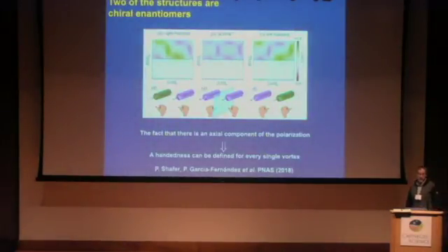And we can define a hand for all of them. So to do this, just take your right hand and then curl the fingers in the direction of the arrows. And then if your thumb is pointing in the same direction as the axial component, then the vortex is right-handed. If not, it's left-handed. So making this trick, we can see how the two vortices here are right-handed, the two vortices here are left-handed, and here in the middle I have one that is left and another one that is right. So we can say that we have here two structures that are chiral enantiomers, this one and this one, while the center one is achiral.